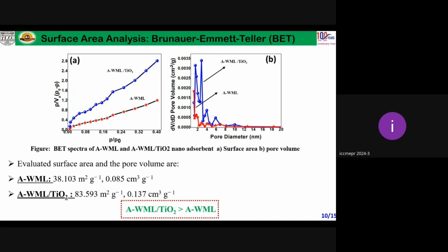No doubt, surface area and pore volume are important parameters for better performance of an adsorbent material. So BET analysis was carried out, and through it, it was observed that the surface area and pore volume of our nanoadsorbent, which is composed of TiO2, are very much higher than those of the adsorbent material, which is basically due to the presence of TiO2 nanoparticle, as I've already mentioned in the introduction to nanoadsorbents. These nanomaterials have a high surface area to volume ratio.